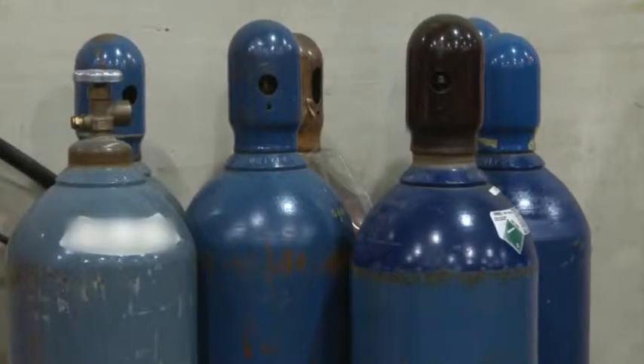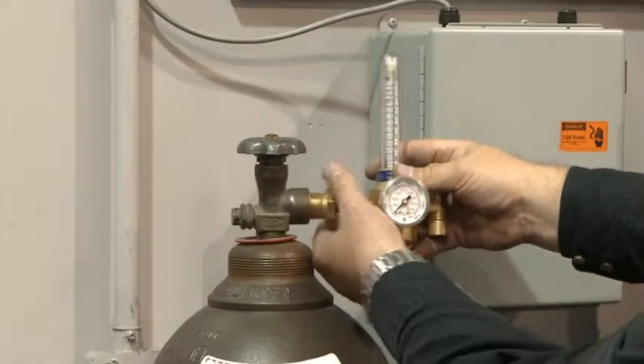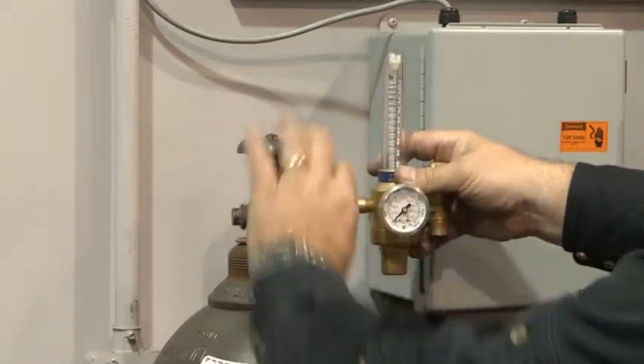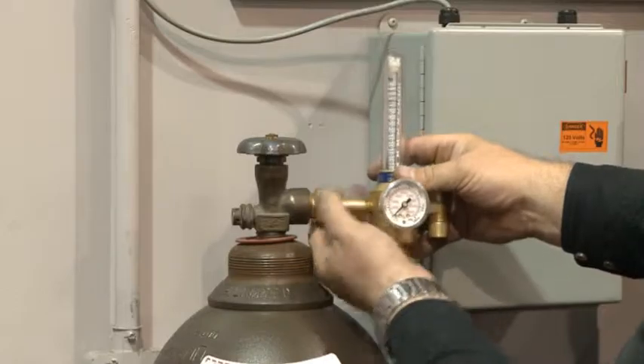You see examples of this when you have water staining on aluminum — the oxide grows thick and it's milky in color because it contains moisture. If you try to weld a water stained plate without removing the oxide, that trapped moisture ends up as part of the weld. Hydrogen can also arrive in the gas, which is supposed to be dry, but even small amounts of contaminated gas will pollute the weld such that it won't pass a specification.